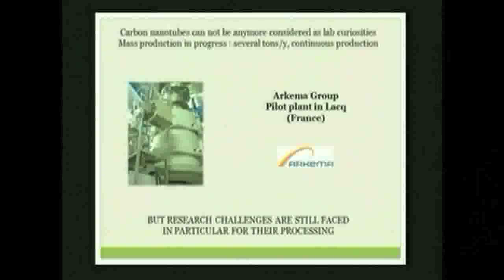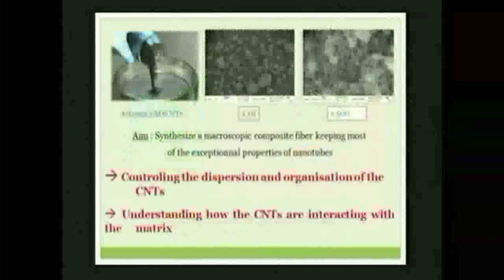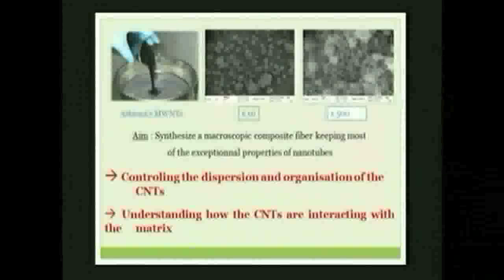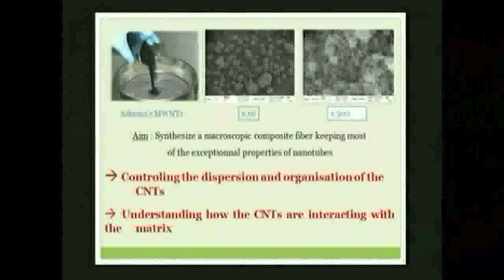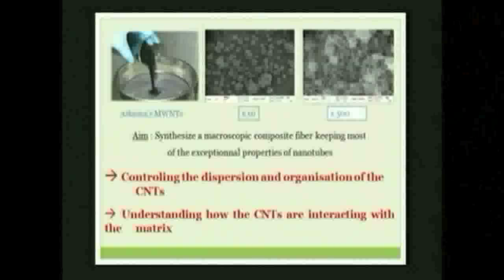Okay, this is good news. Another piece of good news is also that carbon nanotubes can no longer be considered a lab curiosity. Now mass production is in progress, and we have been working in our group with the Arkema group, which is able to produce carbon nanotubes at high rates, high yields. So of course it's very important to aim at the composite market. But there are still many research challenges to process these carbon nanotubes. Why? Because the raw powder that you see here, when you look inside this raw powder, you will see that the nanotubes are completely entangled, disordered. They look like this, so they are very far from the ideal.